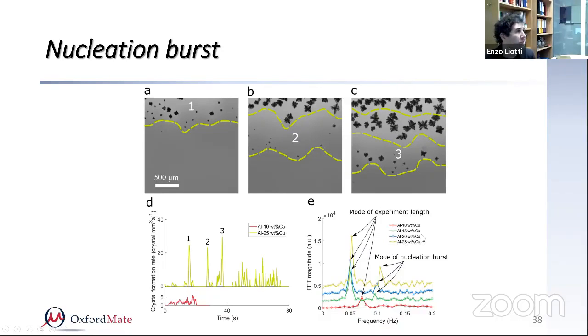So when we have more solute, these bursts are more frequent, so they take place at a higher frequency, and they are more intense. The effect of solute is that when you have a low solute content, nucleation is almost continuous, in the sense that it happens very infrequently and very slowly. While the more solute you put, you favor the formation of a solute suppressed zone, and therefore when nucleation takes place, it happens in the form of a wave, of a burst.